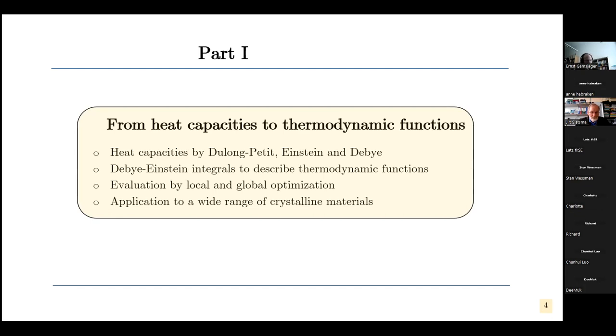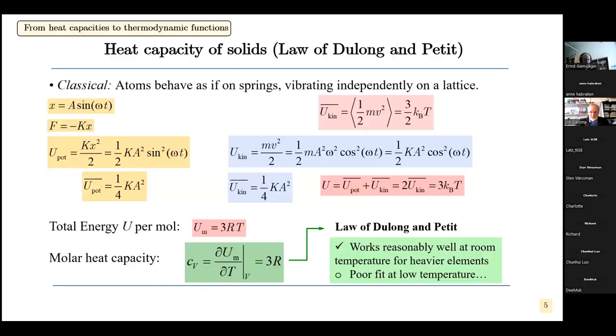To introduce the heat capacities, classically one thinks of atoms which behave as if on springs. The elongation is a sine function of time and the force is proportional to the elongation. One can calculate the potential energy, which is then a function of time, and also the mean potential energy.